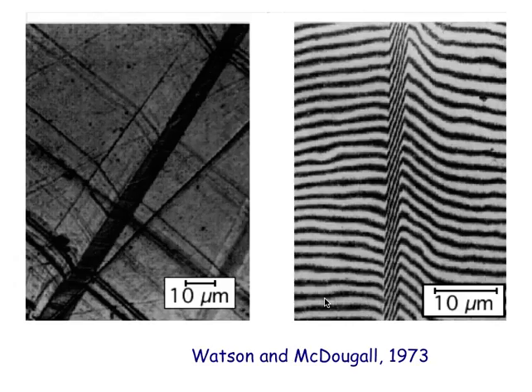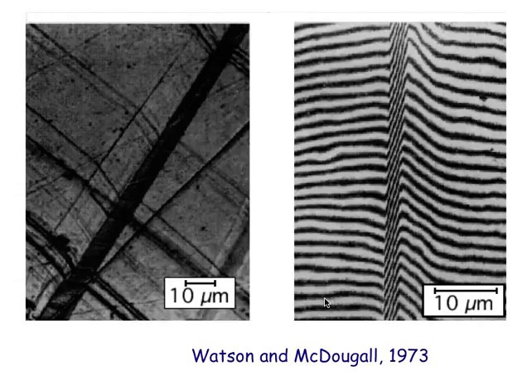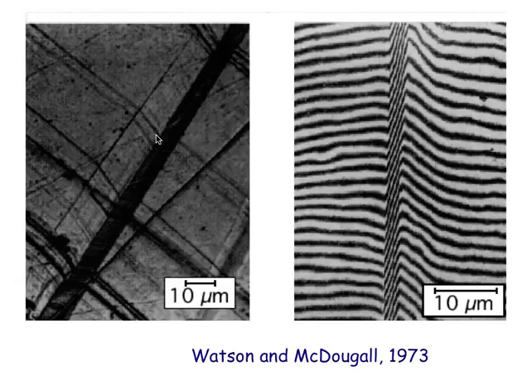We can look at the displacements caused by the transformation in a number of different ways. With bainite we used atomic force microscopy because the plate size is very small — you need to resolve something less than a quarter of a micrometre. But if you have scratches on your austenite before it transforms, the scratches themselves are deflected. If you look here, this is a scratch which was present in the austenite as a straight scratch and it has been deflected by the formation of Widmanstätten ferrite.